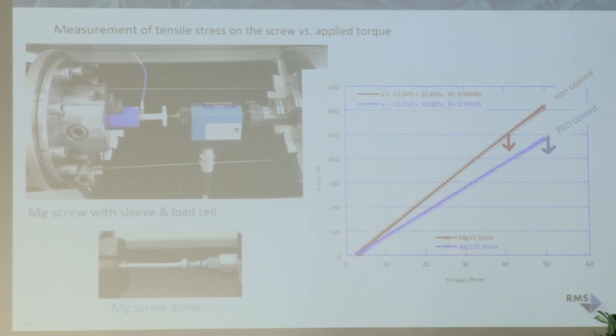We wanted also to see what the effect of stress corrosion is on this. So if you insert a screw, the screw is under tension. So we did a torsion test. This type of screw would fail probably at 60 to 70 Newton centimeters. And now we inserted a cylinder, and we put this cylinder under compression, and with this pressure sensor, we could measure actually the tension on the screw.